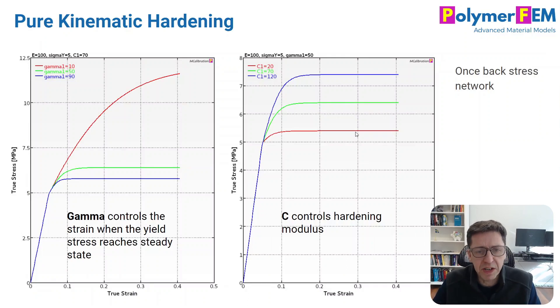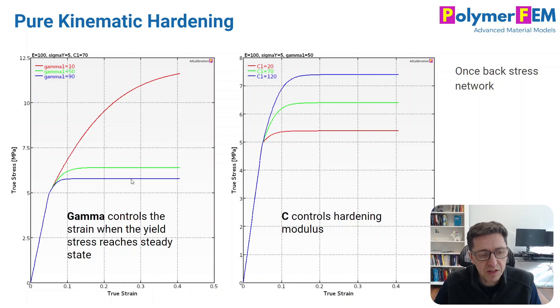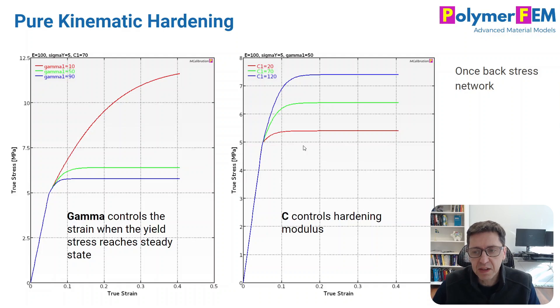To visualize this, the left figure shows stress-strain curves for different gamma values, keeping all other parameters the same, generated using MCalibration's parametric study. A very high gamma gives a rapid approach toward the steady-state stress; otherwise the stress rises more gradually. The c parameter controls the initial modulus after yielding — a low c gives a low slope that increases as c increases. Having multiple kinematic hardening back stress networks, which you superimpose together, gives a smoother, more accurate curve.